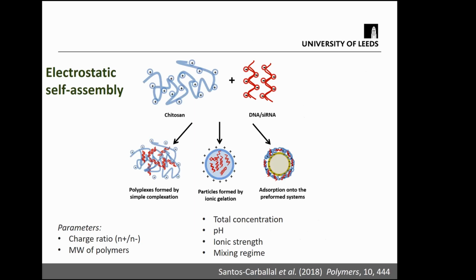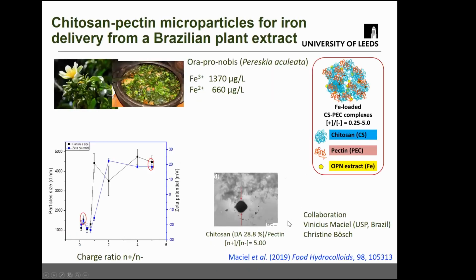Okay, now I want to talk briefly about electrostatic self-assembly. Basically, one of the features of chitosan is that we can easily, nicely mix it with oppositely charged biopolymers, including, of course, nucleotides, DNA, siRNA. So by playing with the mixing ratios, the molecular weights and other parameters, it's possible to obtain different types of complexes, either these simple complexes or particles, for example, if you also use TPP, or to adsorb at the surface of nanocapsules.